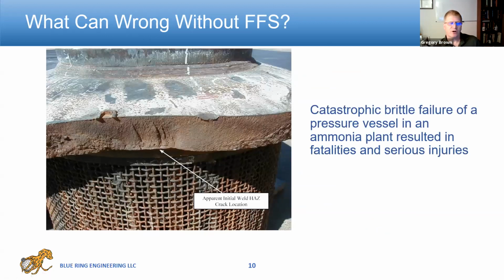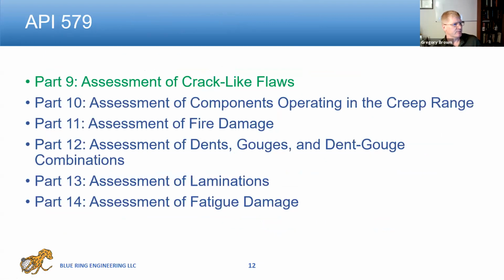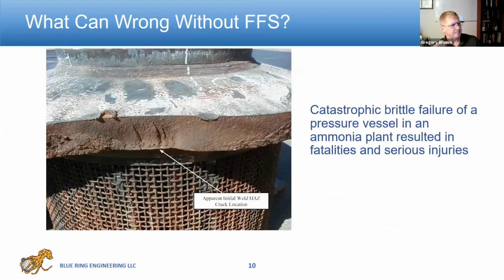What goes wrong without fitness for service? This is really what we want to avoid. What you're looking at here is the failure of a large pressure vessel. The thickness of this pressure vessel, I think, was on the order of 6 to 8 inches, 200 millimeters, something like that. And what you're seeing is this failure occurred because a crack near the weld, what's called the heat affected zone, started, and then upon pressurization, it immediately propagated in a brittle fashion, went through the entire pressure boundary, the entire wall of the vessel, and actually caused catastrophic failure.